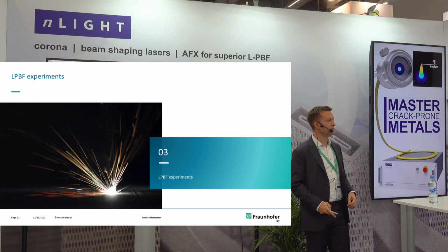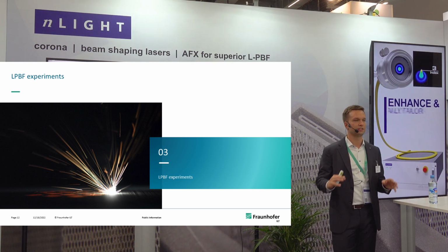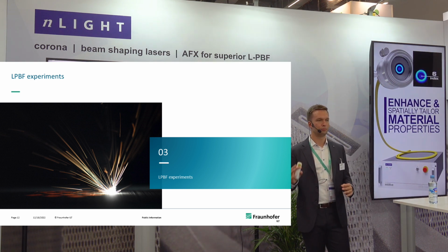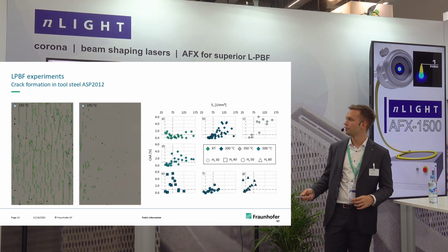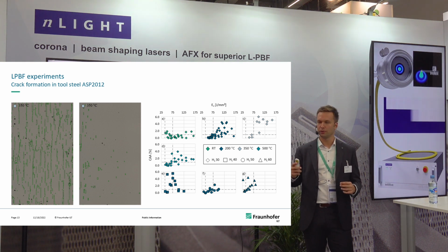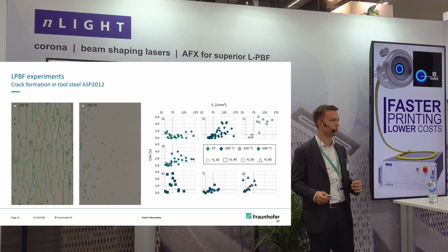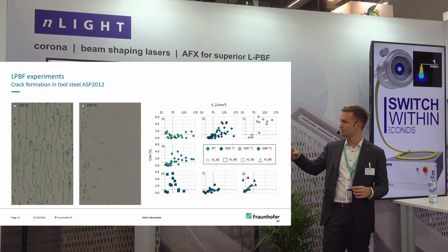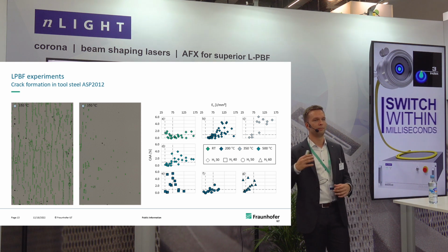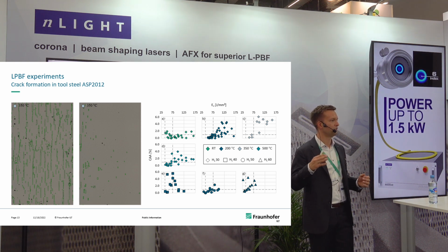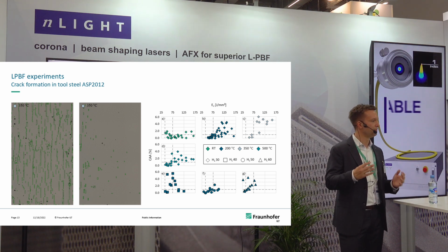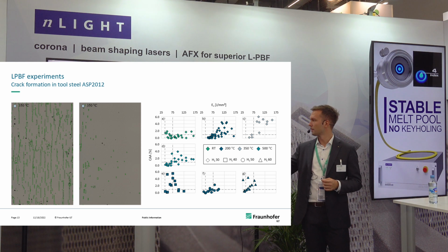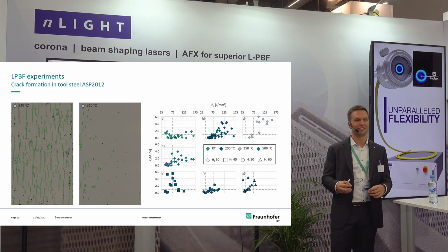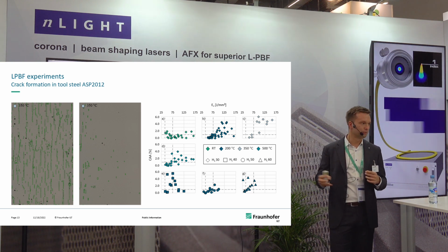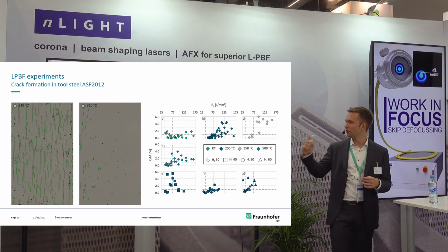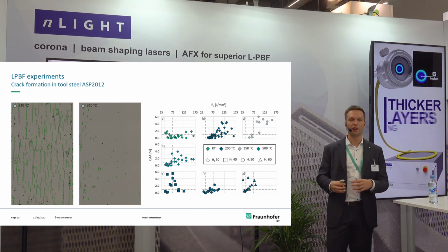Then when it comes to the experiments, we first did some baseline experiments, so state-of-the-art Gaussian beam, preheating, temperature variation, and build-up of multiple specimens. We have some software tools in-house to analyze the cracks that are forming during processing, and are then characterizing the crack density, so the amount of cracks or the cumulated length of cracks per square millimeter, centimeter, however you want to put it. So there you can see that for all the different layer thicknesses, preheating temperatures, and also energy densities, you will in some way end up with cracks.